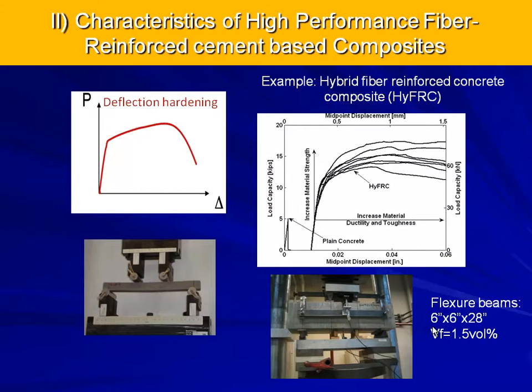I will talk about that one later on. This is tested, we always test this with large beams, so this is a 6 by 6 by 28 in flexure. Volume fraction is 1.5 volume percent. And what you see here is this is not reinforced. It is just the plain material itself, no reinforcing bars. What you see here, this is your plain concrete, and this is your high-performance fiber-reinforced material. So you have here an increase in ductility, but also an increase in strength.